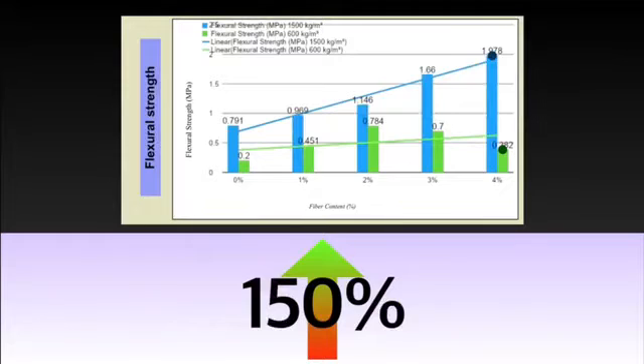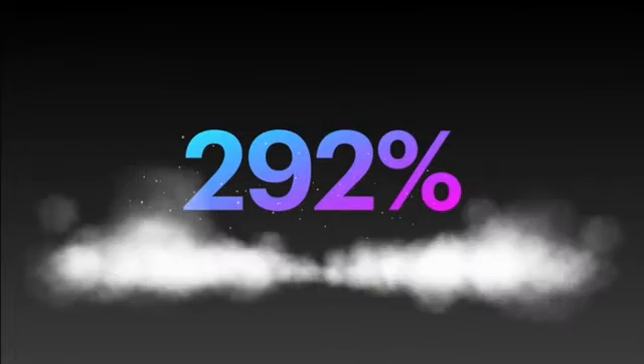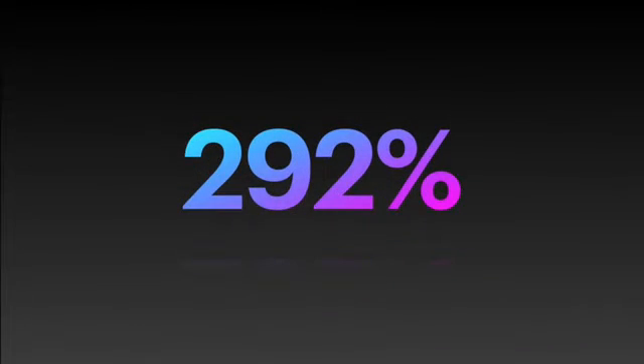You might be wondering, where is the reading for lower density Pulpcrete? For lower density Pulpcrete, we are pleased to announce that we have an increment of 292% when compared to normal non-reinforced foam concrete. This means that the flexural strength of a low density Pulpcrete is almost 3 times better than a normal non-reinforced foam concrete.